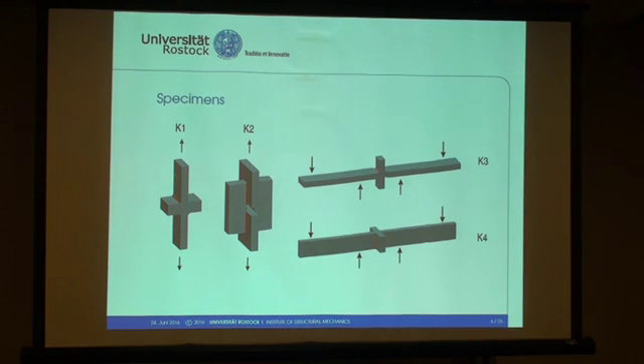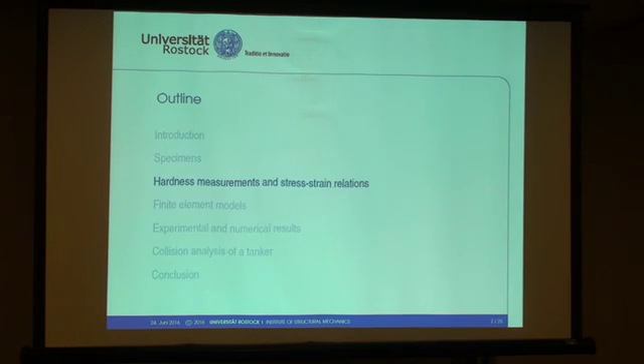I want to show the specimens I used, four different ones, K1 to K4. K1 and K2 are loaded with tensile forces in different directions to the weld joints. The weld joints are here in orange, and K3 and K4 are loaded with a constant moment. All 4 specimens are loaded until fracture.